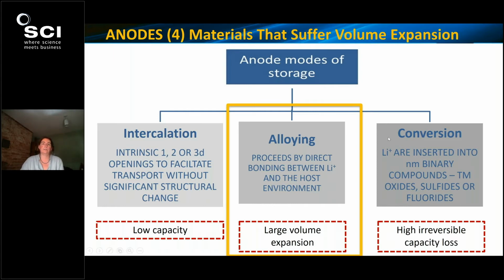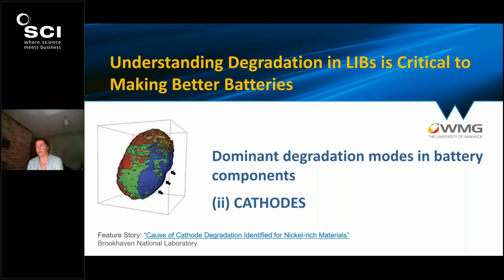But the third type of lithium insertion in anodes has looked at conversion materials, which do a direct chemical reaction to form different compounds. Oxides and fluorides are typical materials, but these have had less success in a commercial sense because you do get a very high irreversible capacity loss, because not all of the chemical reactions that these materials take part in are actually reversible. And lithium-ion batteries rely on having this reversible flux of lithium ions between electrodes. Okay, so that's the anode, it's one half of the battery. So the other side, the cathode or the positive electrode, has another set of degradation mechanisms, which we will now have a look at.